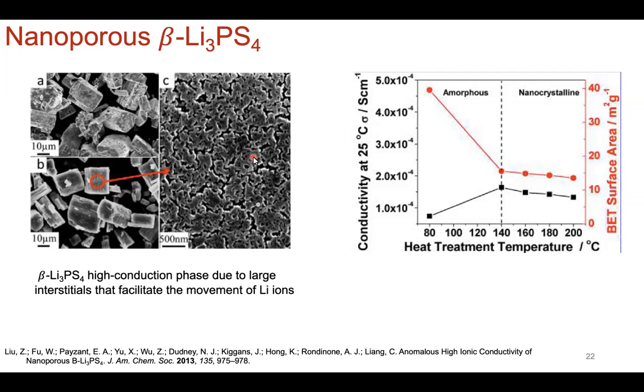And then what temperature you anneal the product at to remove the tetrahydrofuran really impacts the ion conductivity that you achieve. So if you heat treat it to 80 degrees Celsius, you can see the ion conductivity here. But then if you increase the thermal annealing conditions to 140 C to remove as much of the tetrahydrofuran molecules that are coordinated to the beta Li3PS4, to dry off the system, you see the ion conductivity increasing quite a little bit. And then it sort of decreases after that, but there are no error bars here. They all look pretty close to me, so I wouldn't over interpret this data set, but there is a significant enough increase here that I would say that's pretty real. So that's pretty exciting.